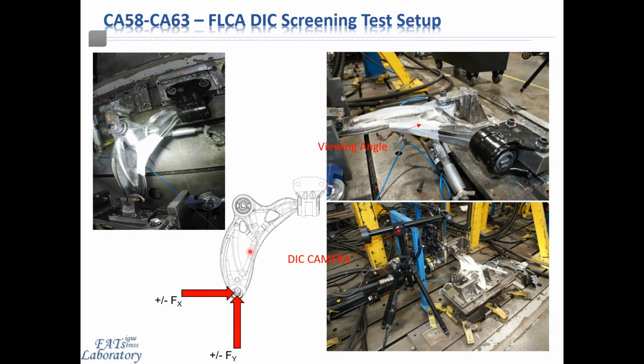One of the unique scientific contributions of this particular work is the fact that we utilized in situ digital image correlation, which was a non-contact technique, and it was utilized to detect material defects and incipient cracks in the fatigue critical regions and monitor crack nucleation, propagation, and the final fracture morphology. An important distinction of this is that it's a non-contact technique that does not require any sensing mechanism to be actually affixed to the surface of the component which you want to instrument.